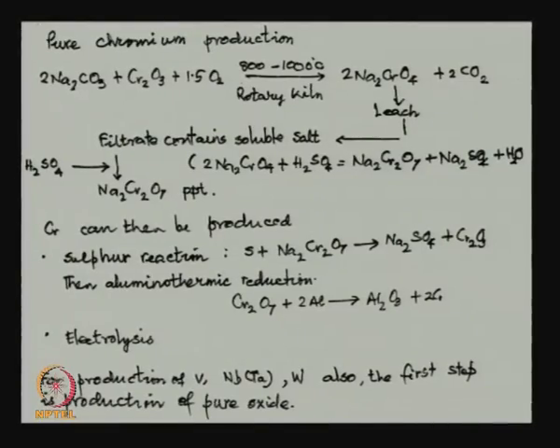To produce pure chromium, a standard technique is to go through a rotary kiln reaction of sodium carbonate with Cr2O3 to form leachable sodium chromate. This reaction takes place in a rotary kiln at 800 to 1000 degrees. Once that is leached, you have Na2CrO4 in solution. By sulfuric acid treatment, we can precipitate sodium dichromate. This is how we do that.